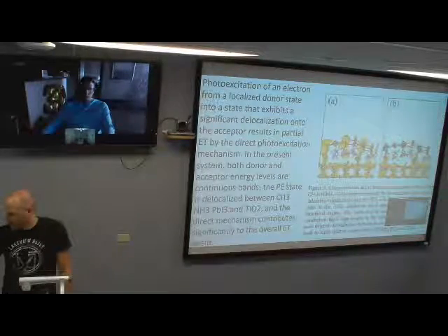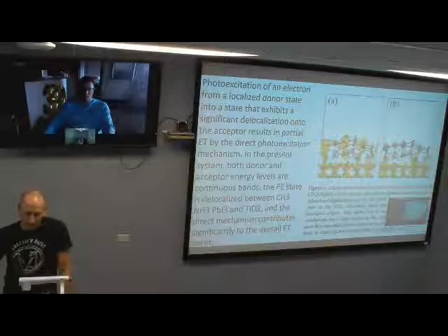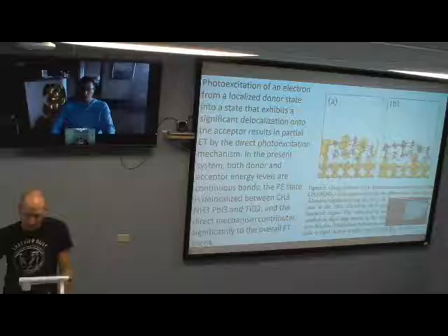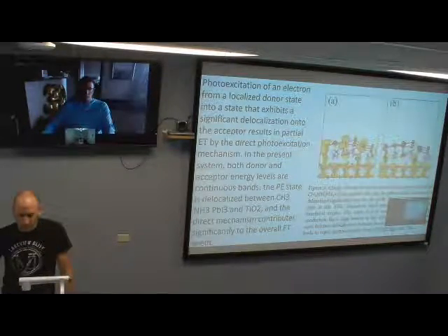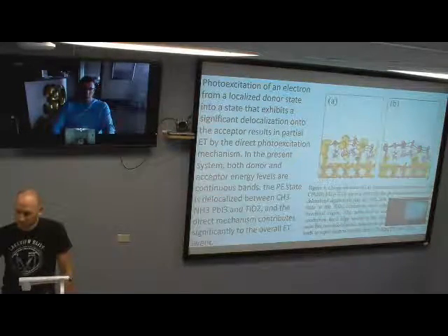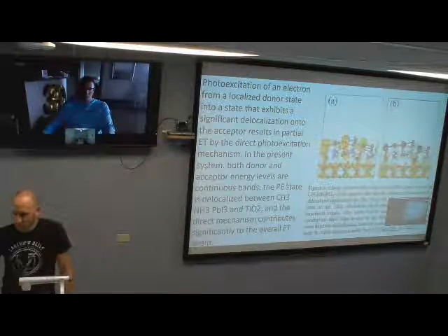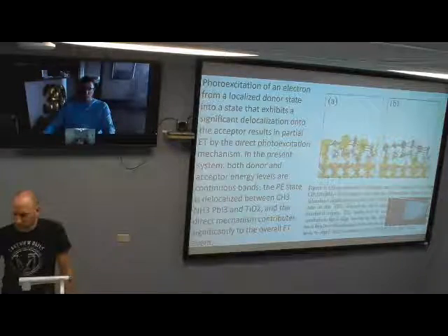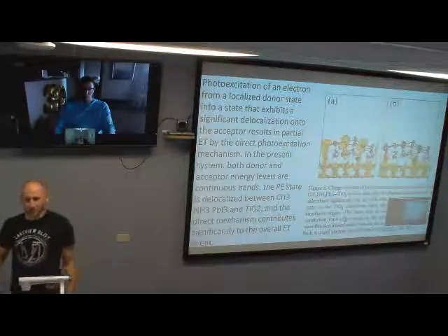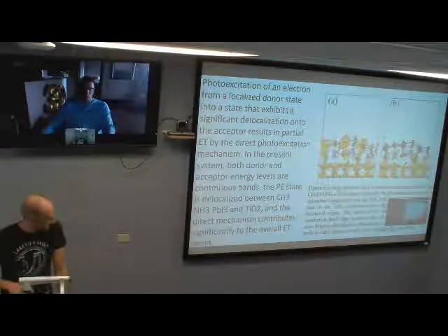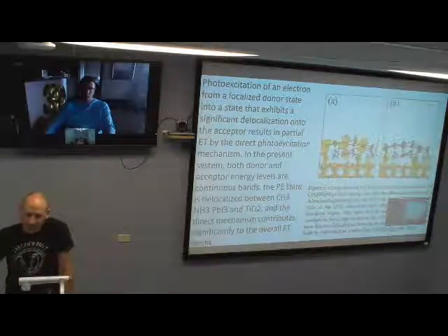But again, the main conclusion of this figure, I guess, is this hybridization, right? Yeah, the direct... what am I trying to say? The direct electron transfer process contributes like 50%. Maybe not process, but just a charge transfer state, because it's not really a process. You shine light and it's immediately there. When your excitation consists of A as a hole where the electron is withdrawn from and B as a conduction band where the electron is promoted to, then excitation made of this pair of orbitals will be charge transfer excitation. Immediately. It just happens at once. Yeah, that's what they call direct photo excitation, right? But they use this as a starting point later to further describe the actual charge transfer. I'm kind of hesitant to say that it's already transferred.